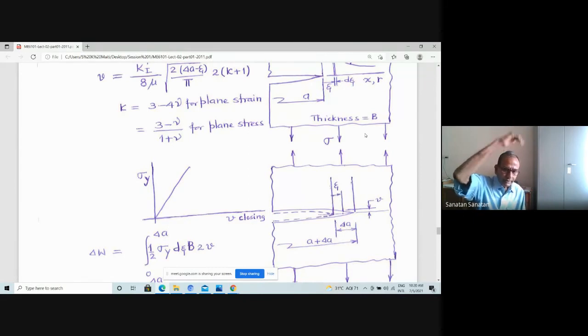So if we plot sigma y versus the gap, it goes like this. So how much is the work? Crack extension is leading to crack opening and becoming stress-free. And if you want to make this extended crack go back to the original crack size, you have to close it, and you have to close the crack faces by distance 2V as given by this solution. The V solution is there at the top.